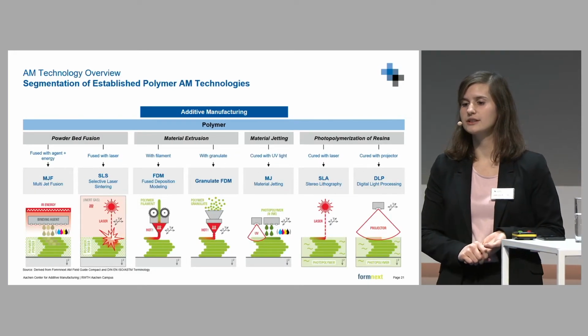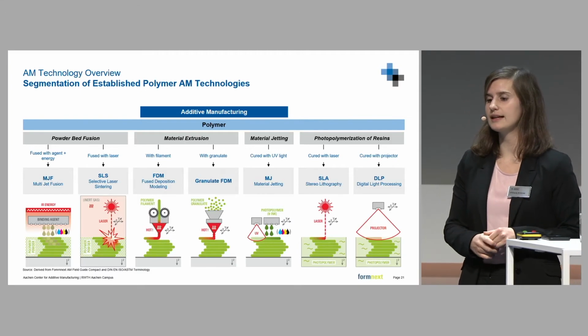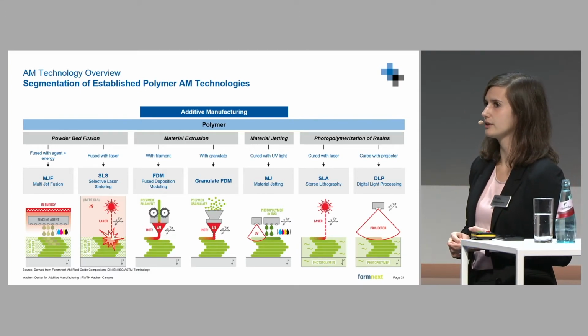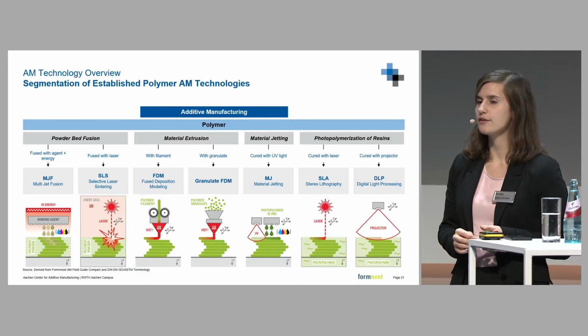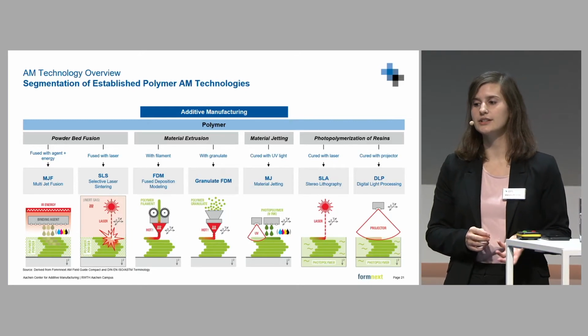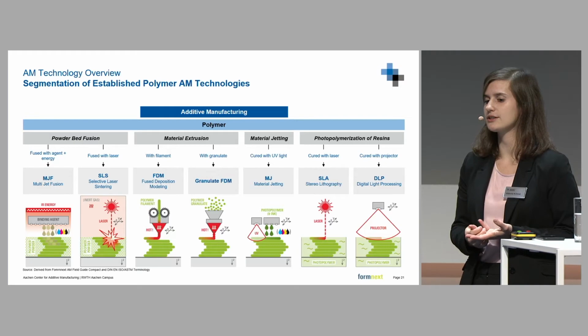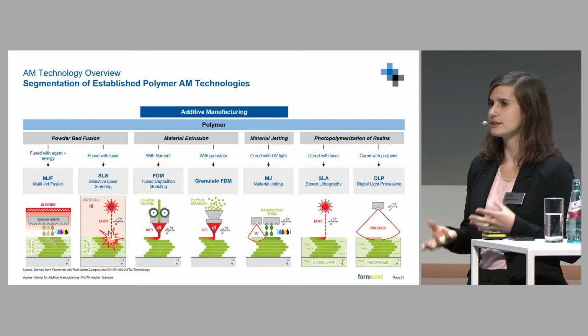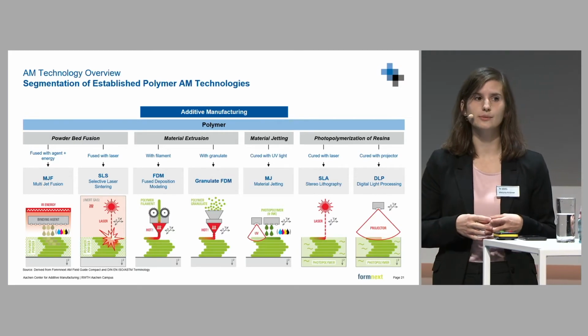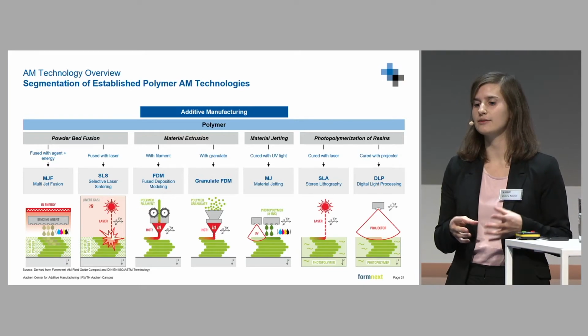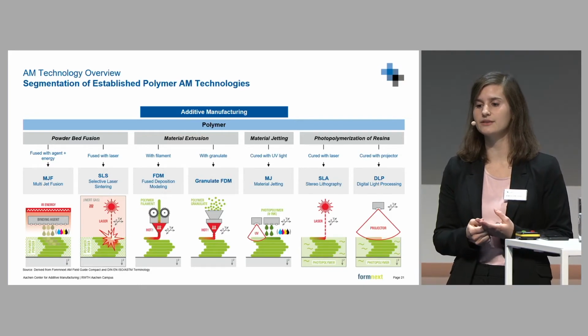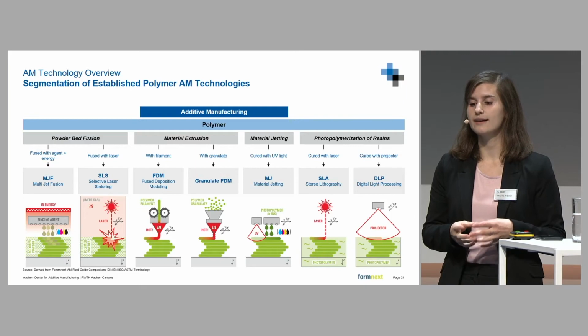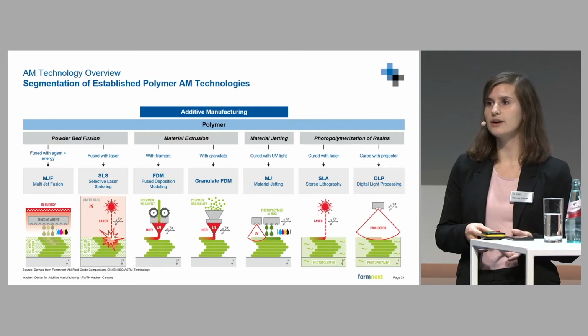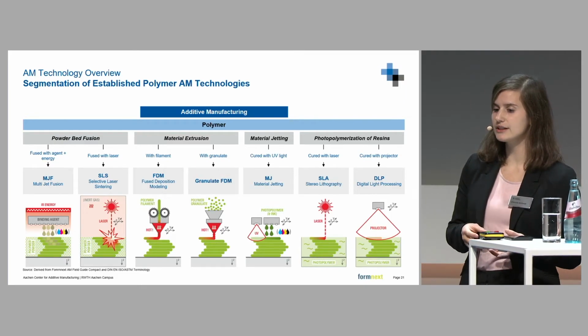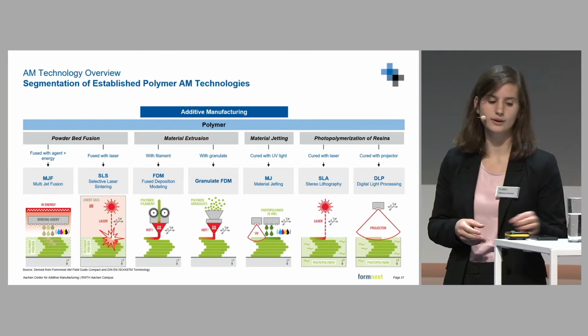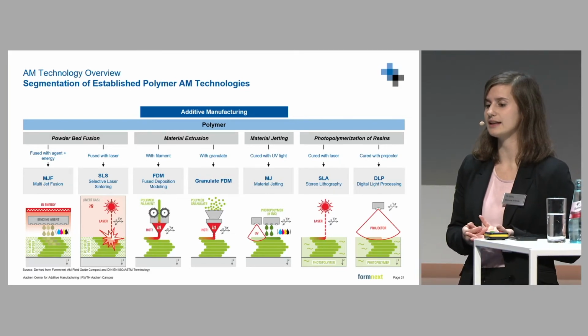So if we look into the segmentation of established polymer AM technologies, we have 4 big categories: powder bed fusion, material extrusion, material jetting, and photopolymerization of resins. And again, as with the metal part, on the left-hand side we have powder bed fusion, meaning that we have a powder stock that's being fused somehow. We have multi-jet fusion, where the powder is fused with an agent and energy, and we have selective laser sintering, where the powder is just fused with the laser.